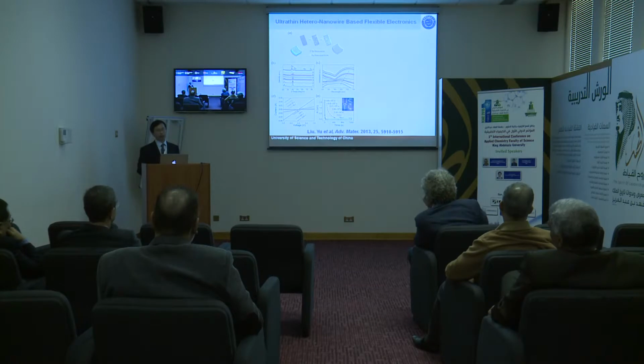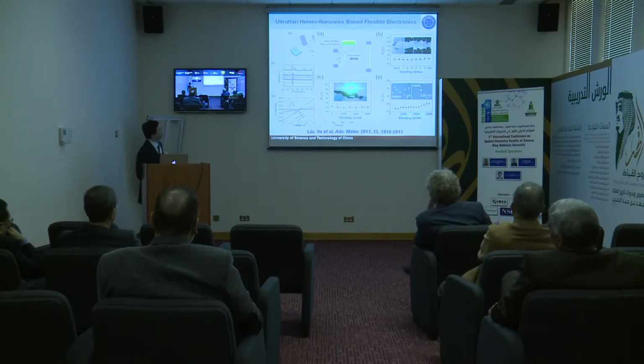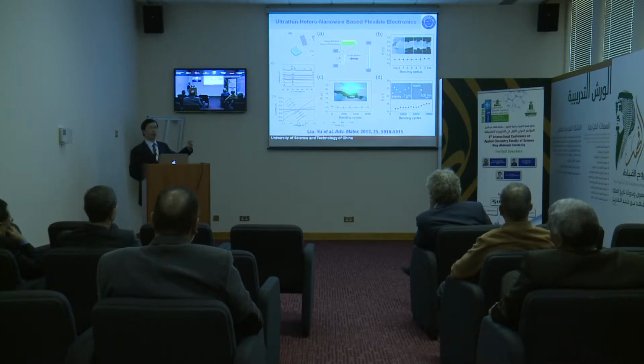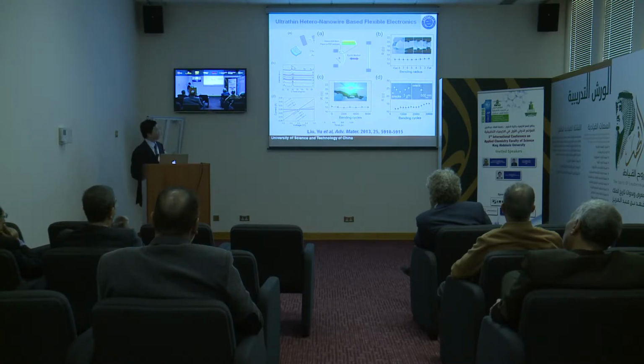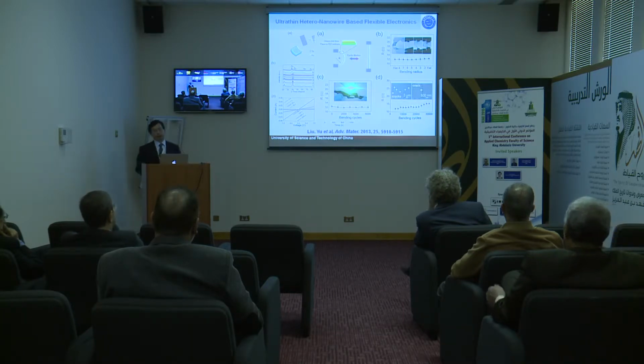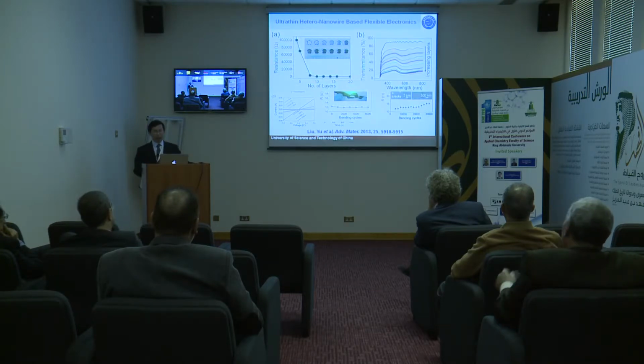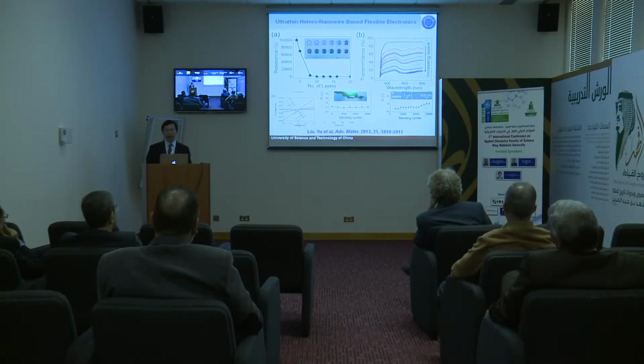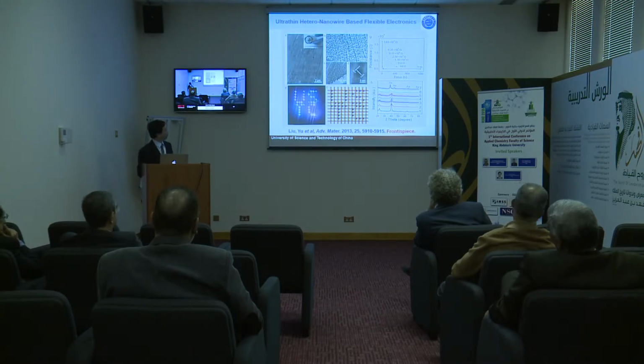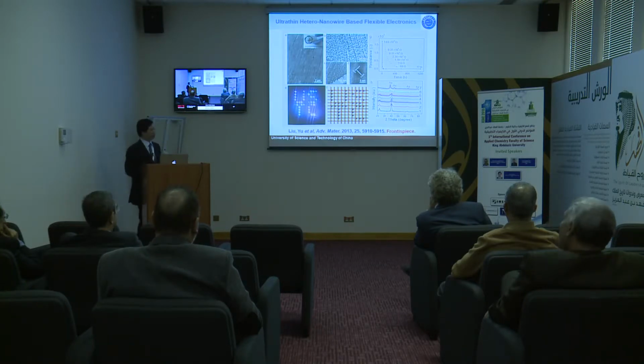tune their conductivity. So one system is that we can use our nanowires as a thin film, as a flexible substrate, flexible electrodes. You will see here some data showing that after many bending cycles, they can still keep excellent conductivity for you to use this nanowire coating to make any surface become conductive in the future. You can even control the transmission efficiency for the light, right? So sometimes you can get a transparent flexible electrode. Here some data is showing if you have a huge area, you can make a huge area become conductive. You can use our nanowire assembled system to make the surface become conductive.